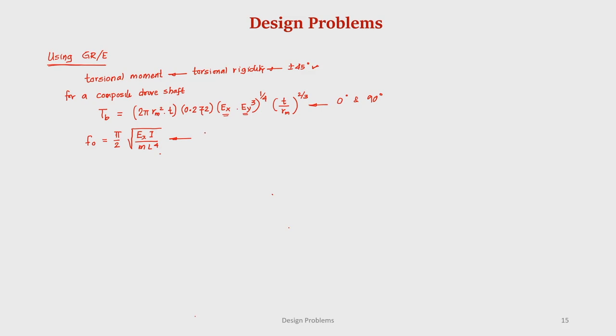Therefore, we must have some 0 degree plies. So, when we decide the stacking sequence, we have to have plus minus 45 degree, we must have 0 degree, we must also have 90 degree plies. So, based on this discussion, we choose 0, we choose plus minus 45, we choose 90 and then a symmetric laminate. If you remember, this is a quasi-isotropic laminate. That means, under in-plane load, it behaves like isotropic. Okay. So, how many plies are there? It has 8 plies.